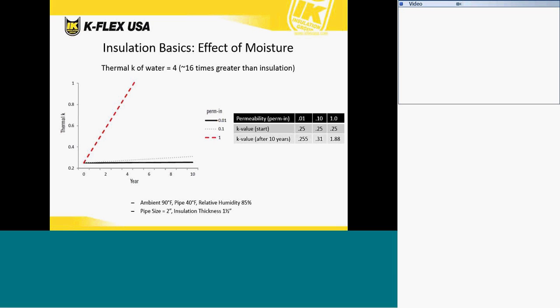However, an insulation system with a high moisture vapor permeability on day one has the ability to accumulate moisture at a fairly rapid pace over those 10 years. And assuming that it does, you have a thermal K, a conductivity, after 10 years of 1.88, which is significantly greater than the 0.25 that you started off with 10 years previous. What that means is that you're going to lose efficiency in the system that's being insulated. You have the potential for corrosion under the insulation, and the potential of mold and fungal growth in that wet insulation. So having a low permeability insulation system is truly key to having constant performance over the life cycle.